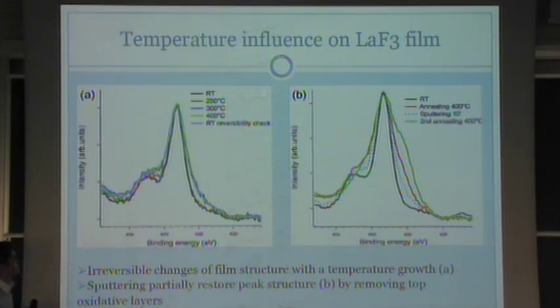Temperature changes show us more or less the same picture. So if you heat, we've got a change of the surface of our structures, and the same low binding energy shoulder, which shows us irreversible oxidation of the surface.